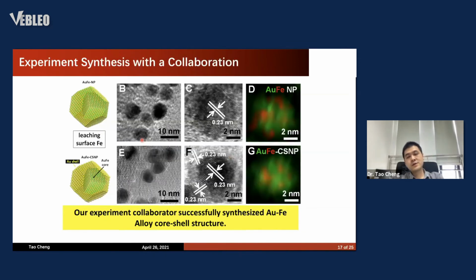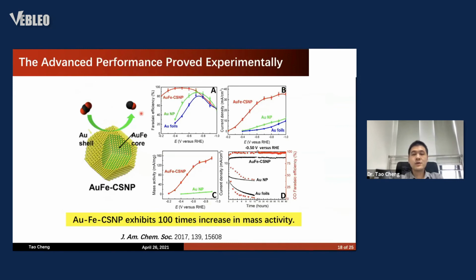The question is whether this is true. We were very lucky to find an experimental collaborator, and they helped us synthesize this nanoparticle. And we did this performance benchmark. We can see that the gold-iron nanoparticle has a 2 orders of magnitude increase in activity. This means that the new catalyst is 100 times better than pure gold. Another piece of good news is that gold is much more expensive than iron. So when you dope iron, you also decrease the cost, and you also end up with significantly better performance. That's really nice.